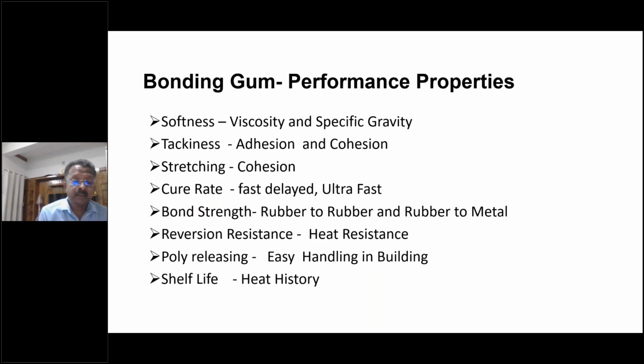Bonding performance properties. Softness. Bonding should be soft. So we have to control the viscosity and specific gravity. Tackiness. Tackiness has 2 aspects: the adhesion and cohesion. Adhesion is a surface phenomenon, adhesion of the bonding surface to the tire surface. Cohesion is the intrinsic strength within the bonding molecules. We need both for getting good tackiness. Good adhesion, good cohesion. Stretching. The people need to stretch bonding while retreading. You should have good cohesion to get good stretching.